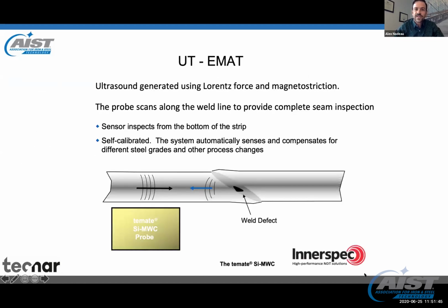I will start covering the topic using the EMAT ultrasounds, which has been there for quite a while. So EMATs, for those who don't know what it is, is non-contact UT. It uses magnetostriction when you have a ferromagnetic material, or it combines magnetostriction with the Lorentz force, which is an interaction between eddy currents and magnetic fields. It uses that to generate a stress in the material that propagates sound. It is mostly used to propagate what we call Lamb waves, which are guided waves that can travel pretty far in the strip. It needs to be in very close range with the strip when you do EMATs. This magnetic field gets weak as you get far from the steel. So the EMAT technology, which is widely used, needs to be in very close contact and needs to follow the strip.